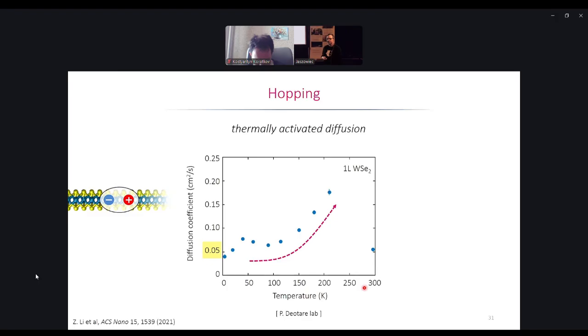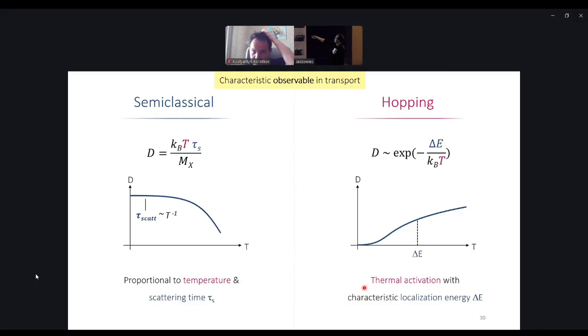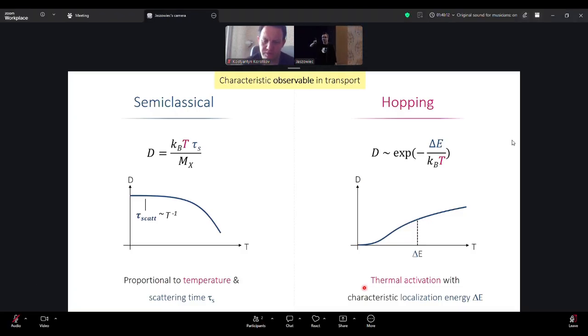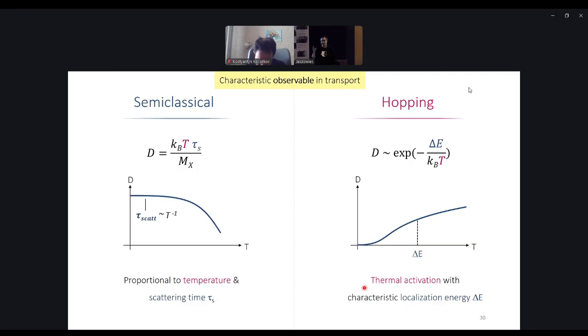For low temperatures, the scattering rate of electrons is not determined only by phonons. So impurities, charge impurities start to play a role. What about the excitons? So this is correct, but in this particular case we're still in the semi-classical regime, depending on the number of impurities. So what you have then, for electrons as well as for excitons, is a scattering channel that is, in this basic approximation, independent of temperature, which means that the scattering rate is a sum of the scattering rate from linear acoustic phonons and the impurity scattering.